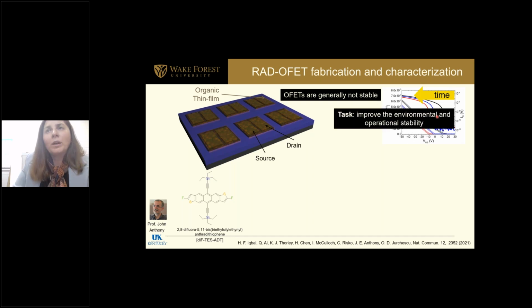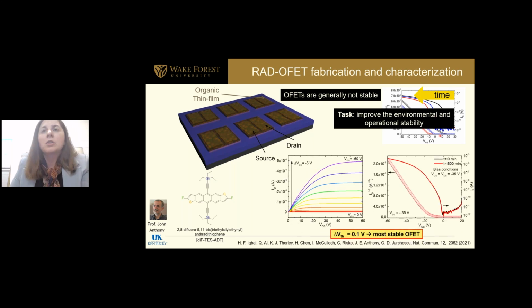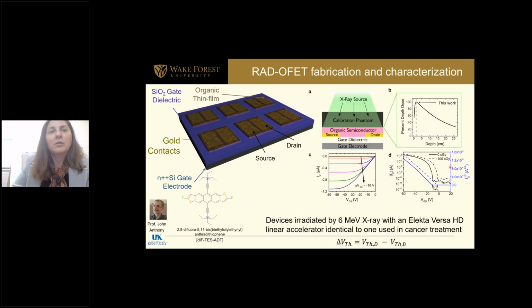So we have spent quite a bit of time to improve this stability that is not related to radiation. And as a result, we have created really highly stable organic transistors. And this is seen here in the very, very small threshold voltage shift upon very aggressive biasing in air, high humidity for a long period of time. So we took these transistors and we incorporated them in radiation detectors.